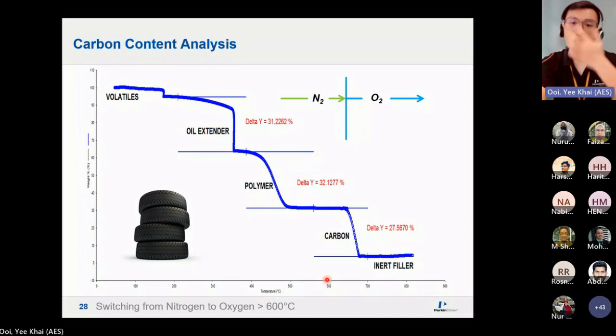So carbon content analysis. This is what it looks like. So volatiles, oil extender, polymer, carbon, and if there is no oxygen, flat line. If there is oxygen, this will come out, and then the residual will be your ash or filler. And when this comes out depends on what is the temperature or the time that you start to flow oxygen. So if I start to flow at 700, then it will come out at 700. If 600, then 600. Okay, so for this weight loss, there is no definite temperature at which you start flowing.